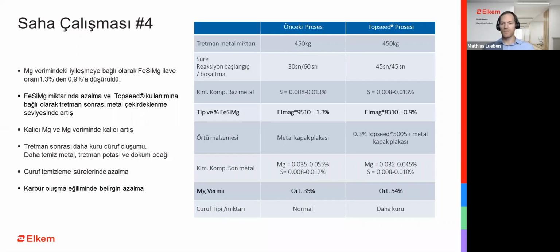There's an increase in the magnesium yield from 35 to now 54%. An improved metal nucleation after treatment due to ferrosilicon magnesium quantity reduction and introduction of Topseed has also been achieved in combination with increased stability of residual magnesium and magnesium yield. Also, the slag is drier after treatment. The iron is much cleaner. And also important, there's a significant reduction of carbide tendency.